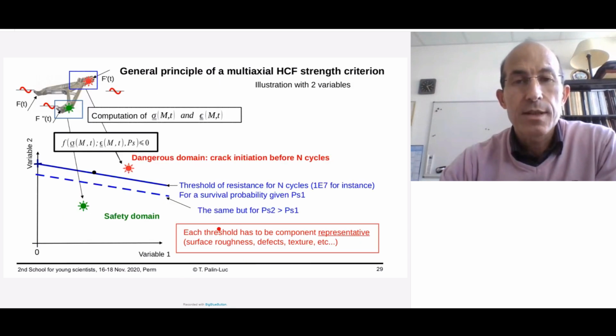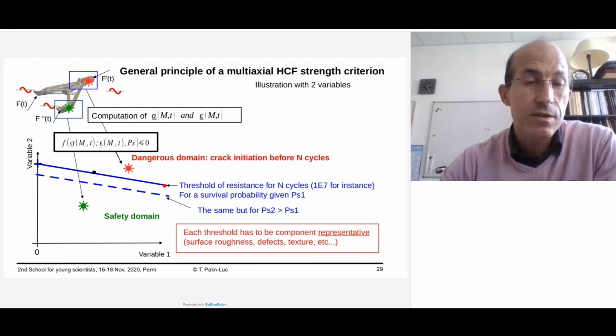What is the general principle of a multi-axial high cycle fatigue strength criterion? This is the following. You have a component here submitted to cyclic loading or cyclic forces. In each point of the component, you compute the stress tensor versus time. Representative quantities of this stress and strain have to be used in equations for a given survival probability. If I want to illustrate that in a two-variable diagram, for the most common criteria, there is a threshold plotted in blue corresponding to a given life, for instance 10 to the 7 cycles, and a given survival probability, typically, for instance, 0.5.